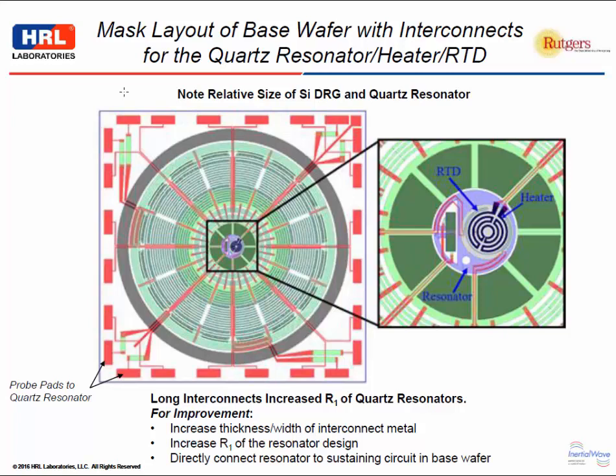You can see how far we had to run the interconnects for the quartz resonator out to the edge of the die. So these are actually the probe pads for the quartz resonator. These long interconnects increase the R1 of the quartz resonator, and I had to take that into account when we did the final measurements. We would try to improve that. We would increase the thickness and the width of the interconnect metal. We could go to a design where the R1 didn't start out at 13 ohms, so the interconnect resistance wouldn't have as big an effect.